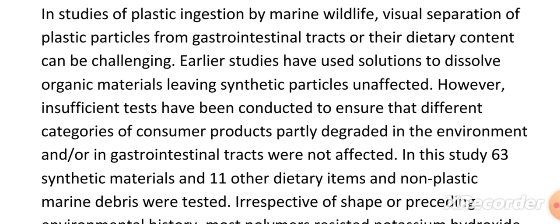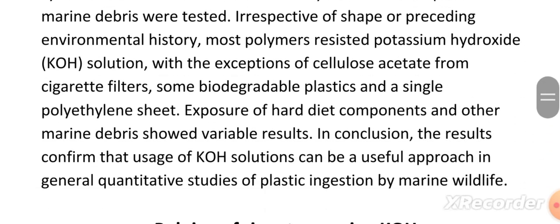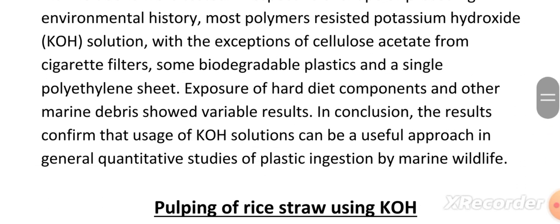Irrespective of the shape and preceding environmental history, most polymers resisted potassium hydroxide solution, with the exception of cellulose acetate, cigarette filters, some biodegradable plastic and a single polythene sheet. Exposure of hard diet components and other marine debris showed variable results. In conclusion, the results confirm that usage of potassium hydroxide solution can be a useful approach in general quantitative studies of plastic ingestion by marine wildlife.